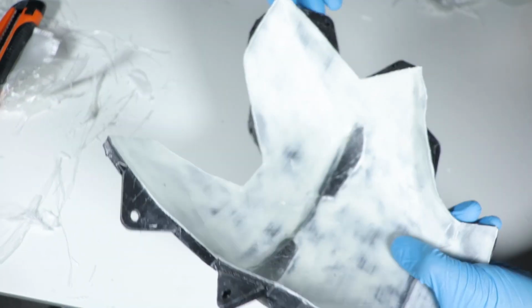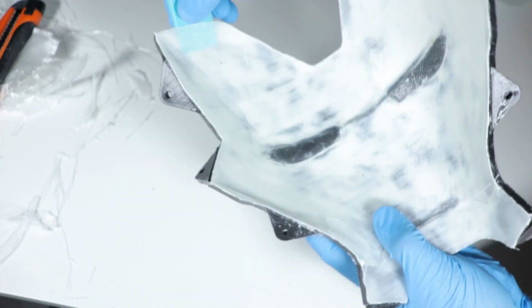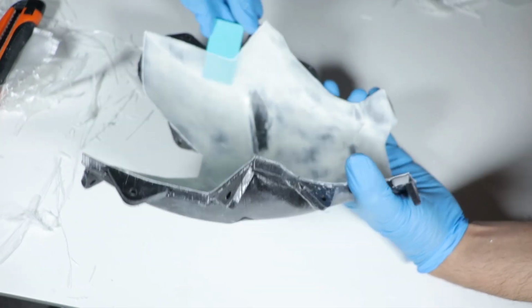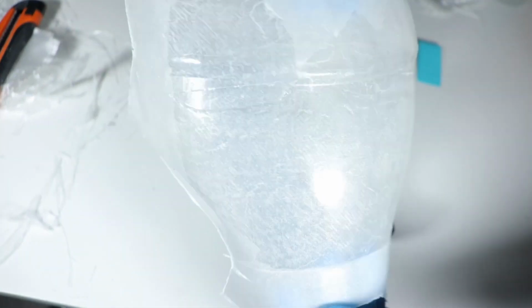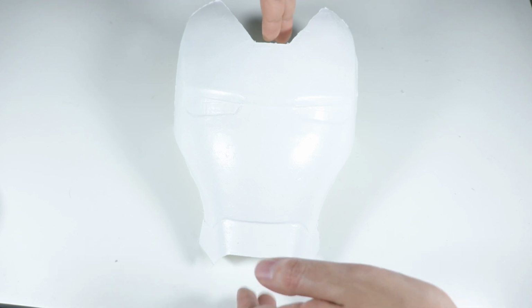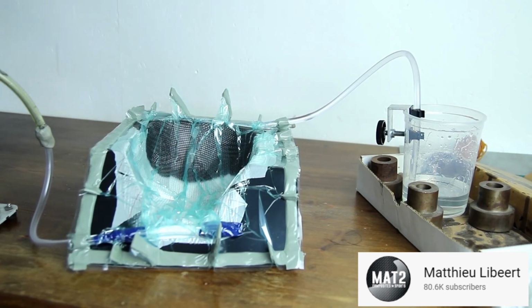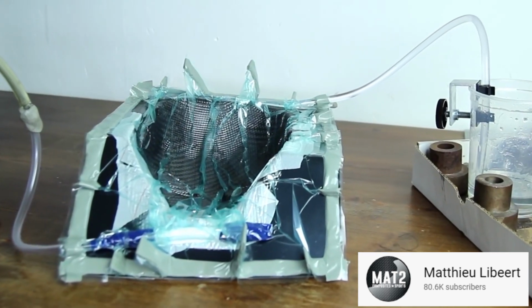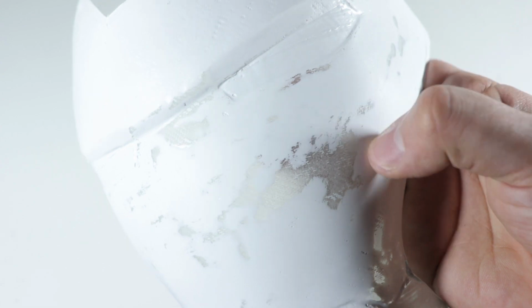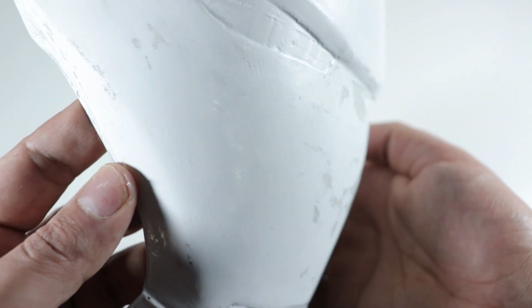Now I can demold the part using a plastic wedge to not damage the surface of the mold, and I'm doing it slowly on every edge. It's looking pretty good so far. You can see all the imperfections after adding a layer of primer. These imperfections come from the fabric used and the fact that the part is laid up by hand. If we use the resin infusion process instead, we would have fewer imperfections. But it is easy to correct that. Just a little sanding and priming two or three times will hide most, if not all, of the imperfections.